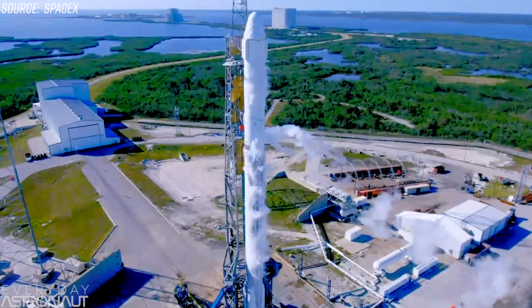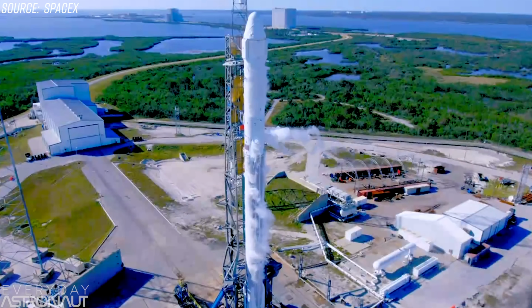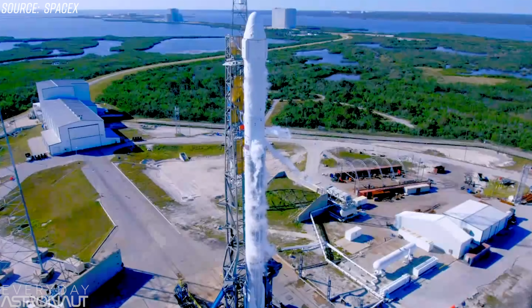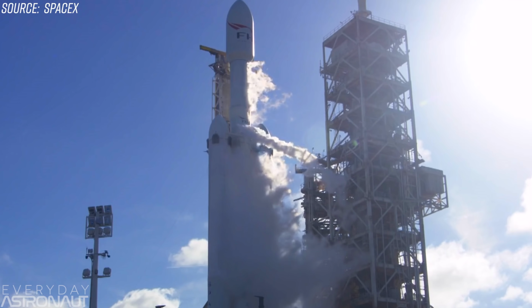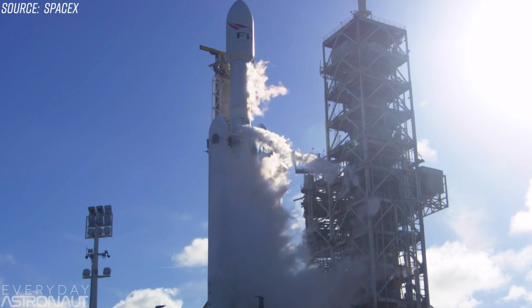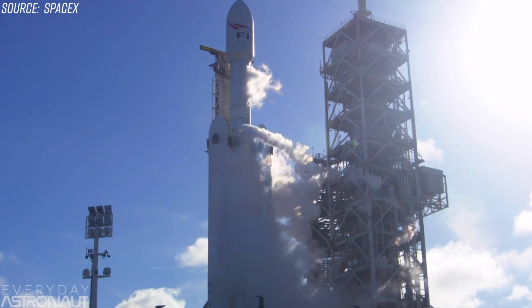The super chilled liquid oxygen that SpaceX puts inside these paper-thin tank walls is an unbelievably cold minus 183 degrees Celsius. And at the exact same time, the outside of that tank can reach temperatures several hundred degrees Celsius on ascent. And we're not even talking about the brutal re-entry temperatures for now. More on that in a second. But it's the cryogenic temperatures that's really truly the key to stainless steel being advantageous.